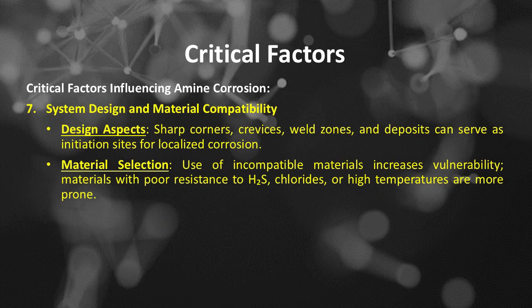Critical factors influencing amine corrosion. Number 7 is system design and material compatibility. Design aspects: sharp corners, crevices, weld zones, and deposits can serve as initiation sites for localized corrosion. Material selection: use of incompatible materials increases vulnerability. Materials with poor resistance to H2S, chlorides, or high temperatures are more prone.